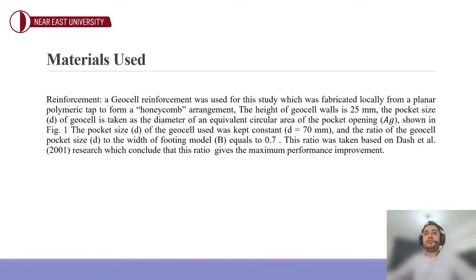Reinforcement. A geocell reinforcement was used for this study, which was fabricated locally from a planar polymeric tape to form a honeycomb arrangement. The height of the geocell wall was 25 millimeters, and the pocket size of the geocell is taken as the diameter of an equivalent circular area of the pocket opening, Ag, which is shown in figure 1. The pocket size of the geocell was kept constant at 70 millimeters, and the ratio of the geocell pocket size to the width of the foundation was equal to 0.7.